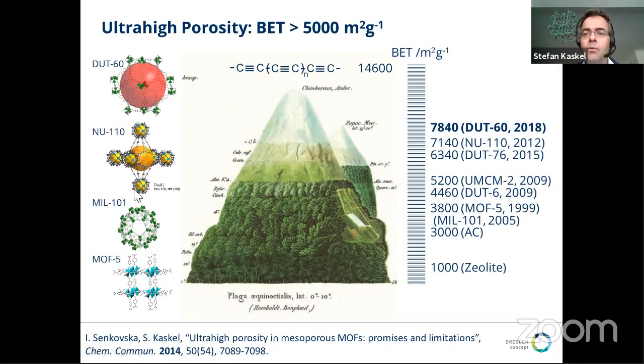And until 2012, NU-110 was the world record in terms of specific surface area. Basically, it had a surface area above 7,000 square meters per gram, BET apparent surface area reported. And in 2018, we reported a new material, which we call DUT-60, which has an even higher apparent BET surface area of 7,800 square meters per gram.